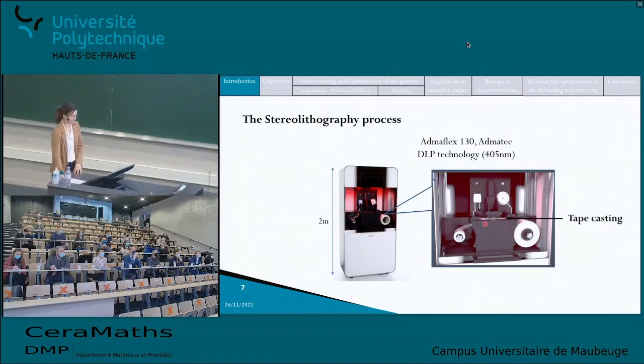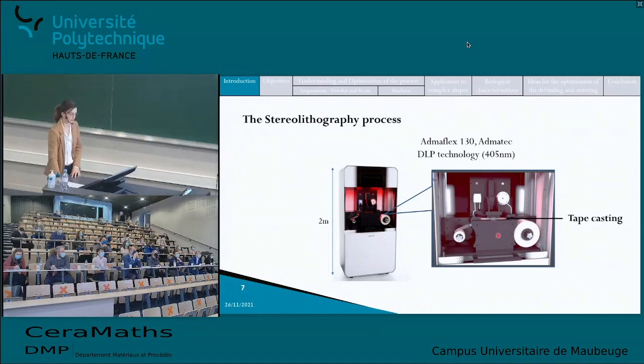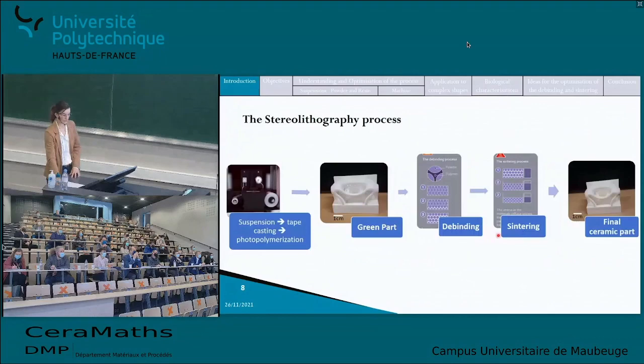As I mentioned, the suspension is cast onto the plastic film and illuminated from below, which leads to its photopolymerization, giving us the green part, where the bioceramic powder is trapped inside the photopolymerized resin. This part then has to go through the debinding cycle in order to remove the binder, and the sintering cycle in order to densify the ceramic powder and obtain the final ceramic part.